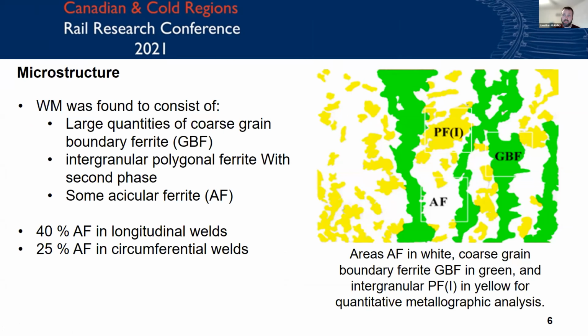What we found when we were looking at the microstructure of these samples was that there was large quantities of coarse grain boundary ferrite in the center of the weld. There was some intergranular polygonal ferrite with a second phase and some acicular ferrite. Acicular ferrite is a very interesting type of microstructure where you have many interlocking platelets creating a very complex structure that has a tendency to be very tough and resilient. And I'll talk a little bit more about that later.